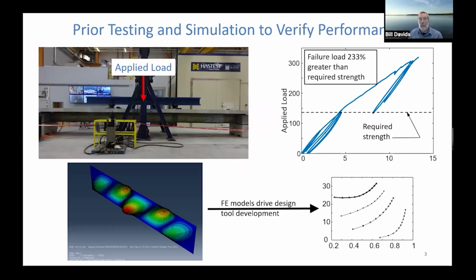Now, we've done a lot of work, testing and simulation, to verify its performance. We've done laboratory testing of girder strength, shown with a 4-point bend test in the photo on the upper left. Some results of the most recent test of that are shown on the right. We're greatly exceeding the required strength because of the design guidelines that we use for the girder, but performance is very good and as expected. We've done a lot of modeling and simulation that is driving design tool development. And this is really necessary because with FRP, there are other limit states that must be checked. There are no closed form solutions. We really have to dig in and do some more advanced analysis sometimes, but we have done a lot of homework to take that off the plate of the design engineer.